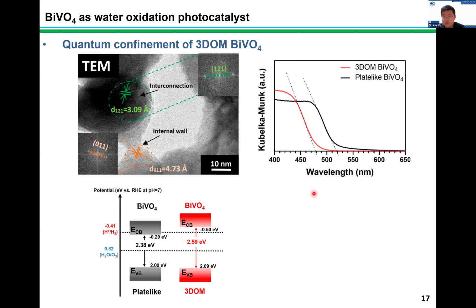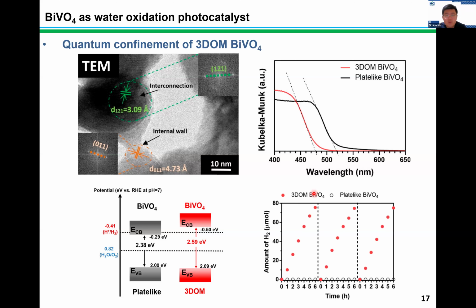So to prove such effect, we did the hydrogen evolution experiments for our two samples with the scavenger of holes, and we found that the 3DOM bismuth vanadate can achieve a very efficient hydrogen evolution and it's very stable, but the bulk counterpart shows limited performance.